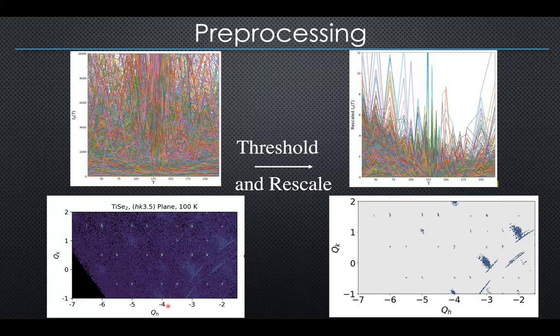Yeah. So the left-hand side is a recording of the intensities from scattering as a function of momentum transfer. That is incoming beam, outgoing beam, and the difference is the momentum transfer. We have three-dimensional momentum transfer, Qx, Qy, Qz, so the data is distributed in three-dimensional space. And here we're looking at a plane. We call xyz hkl, it's just a convention. So QH means X component, QK means Y component. So we're looking at the XY plane of a three-dimensional distribution of data.